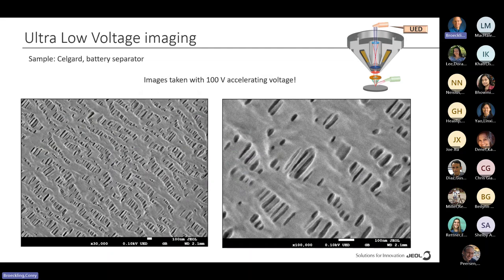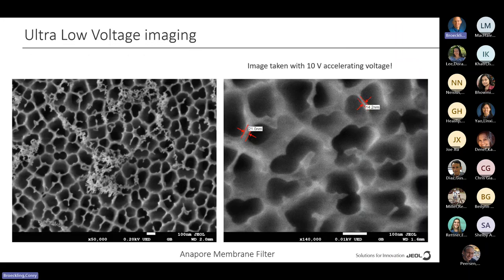Now we're going to focus on what they love to push - low voltage imaging. This is 100 volts. We can't do that in the present microscope. But here's imaging at 100 volts. And look at this - 10 volts. So they actually do imaging at 10 volts. This is for soft materials where you really have problems with them. The advantage of going to low voltage is you hopefully preserve the sample in its pristine form. I hope we can do this kind of imaging here.